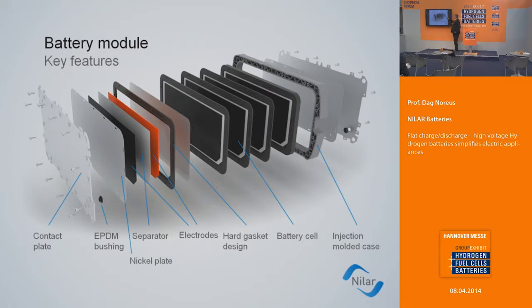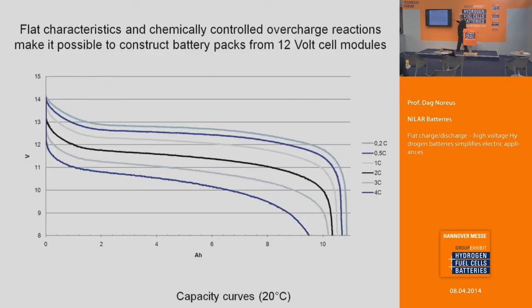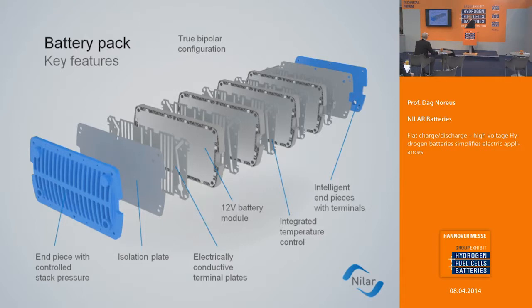By having a flat surface, you can create very uniform electrochemical conditions for the battery. Meaning you have good control of the overcharge and over-discharge. So you can then build modules based on these 12-volt packages. And still with discharge at about 12.5 volt, you have flat characteristics, and you get chemically controlled overcharge reactions. So then you can make these sort of 12-volt modules into larger battery packs. And these modules can then be constructed into high voltage battery packs here. So it's a simple modular system of rather robust battery modules with a stable chemistry, and the chemistry controls overcharge and over-discharge.